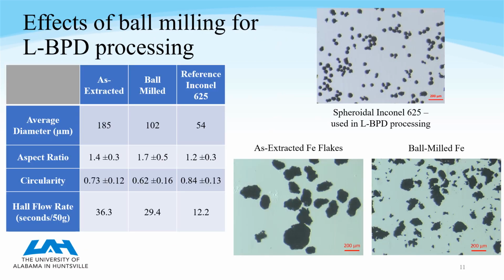Now, here we have a summary of the actual results of the processing. The main takeaways here are that after ball milling, the flakes were smaller, but they were definitely still flakes, and they were actually more irregularly shaped. The aspect ratio went up, the circularity went down. And what that points to is the fact that, again, the flakes weren't reshaped, they were only broken apart. So we have these larger pieces that were maybe halves of the original flakes, and then a bunch of these little tiny pieces that probably broke off in between.